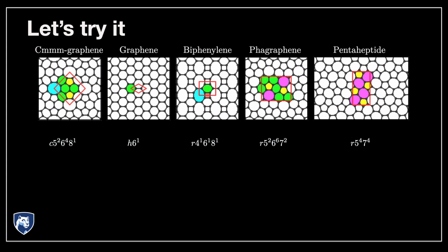And on top of that, they provide you a lot of information. For example, they give you the number of rings. The number of rings is just the sum of all the superscripts. So we have 7 rings, for example. And of course, each ring is basically defined by 2 atoms. You can find that easily from the slide I showed you when we derived the Euler characteristic equation for the sp2 carbon. So we have 14 atoms in the cell.